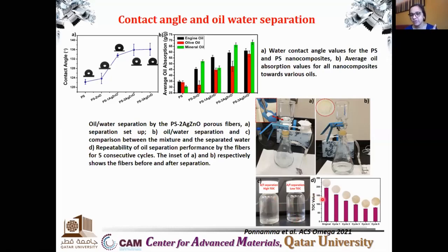And this is the TOC value after subsequent cycles. This is the original, cycle one, cycle two. So we are using the same membranes again and again to test the recyclability of the membrane. We found that up to cycle five, the membrane was perfectly fine. But after the fifth cycle, we noticed that the TOC value is increasing. So the membrane is probably losing its capacity after cycle five.